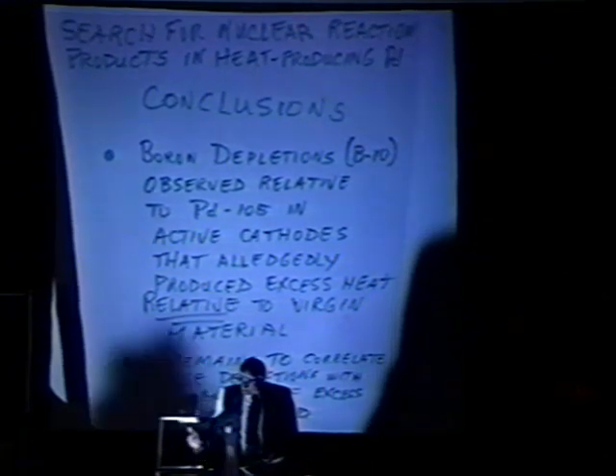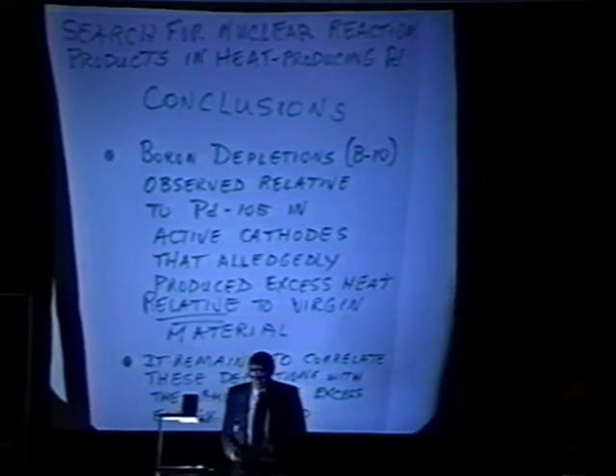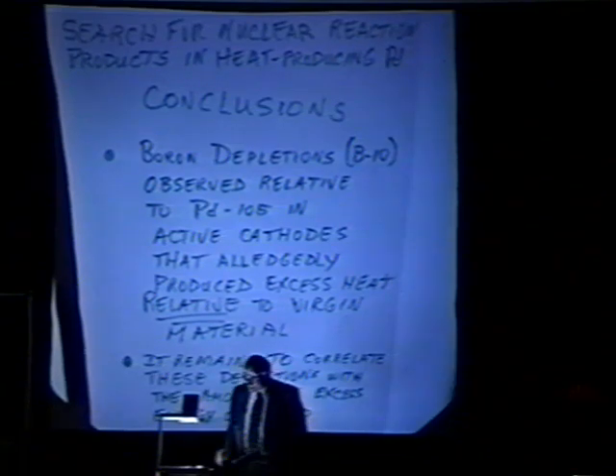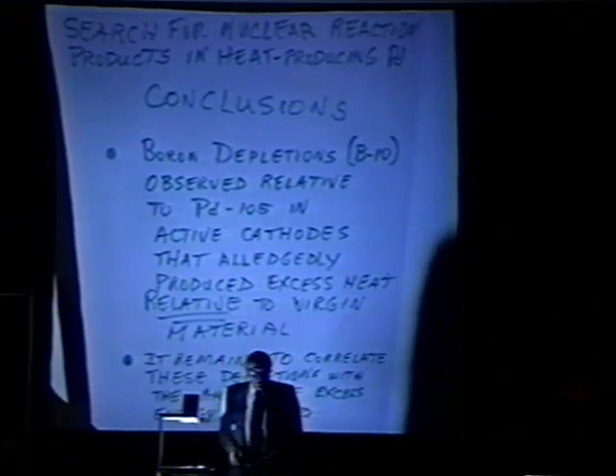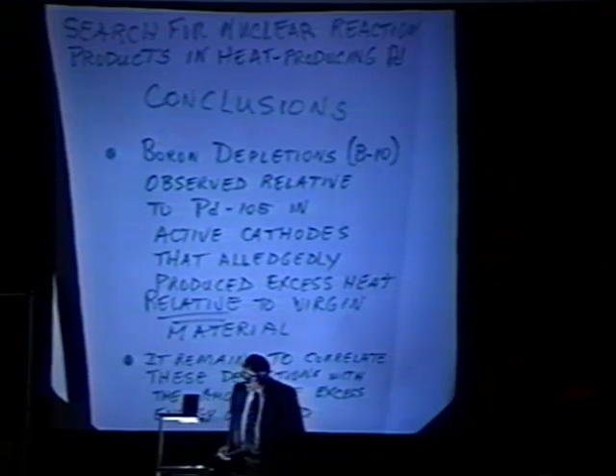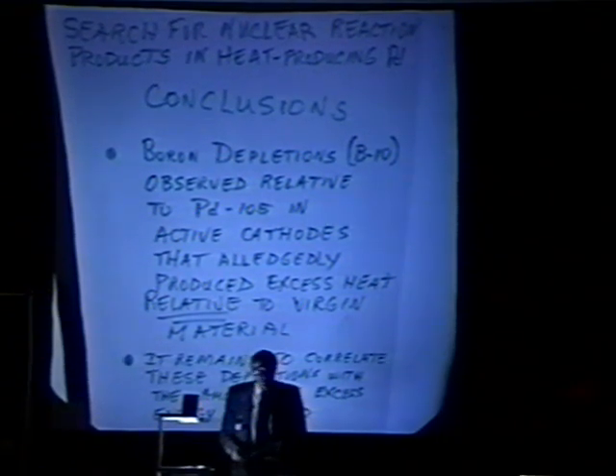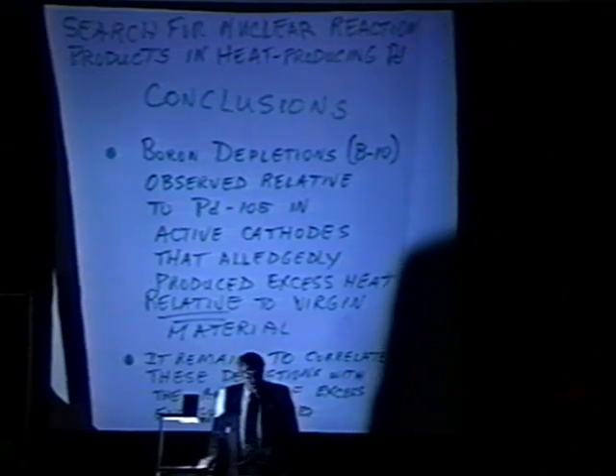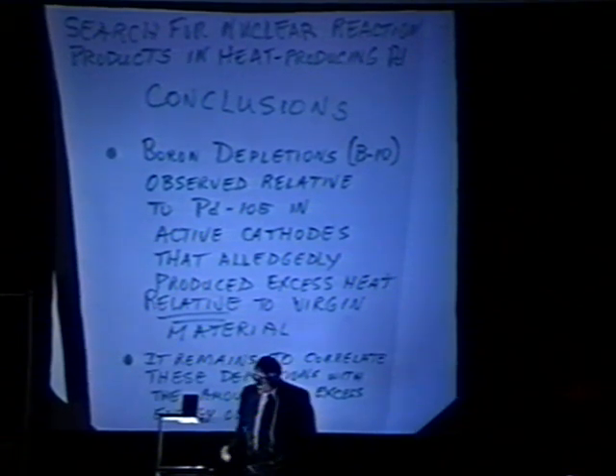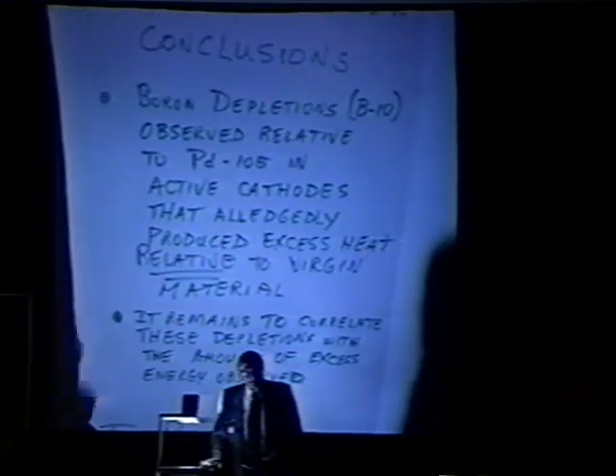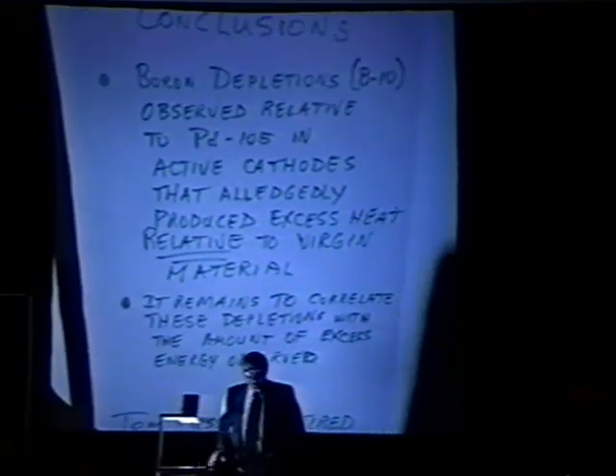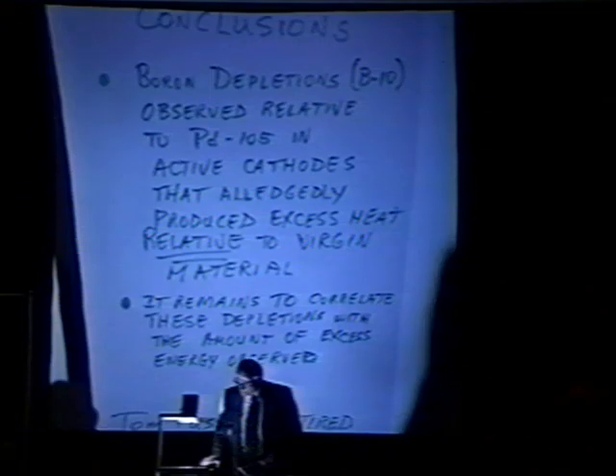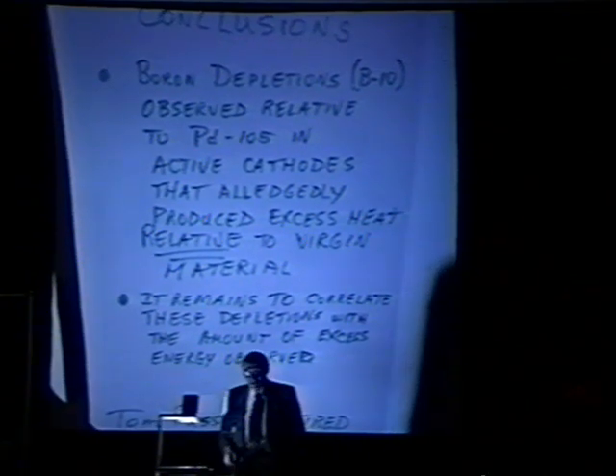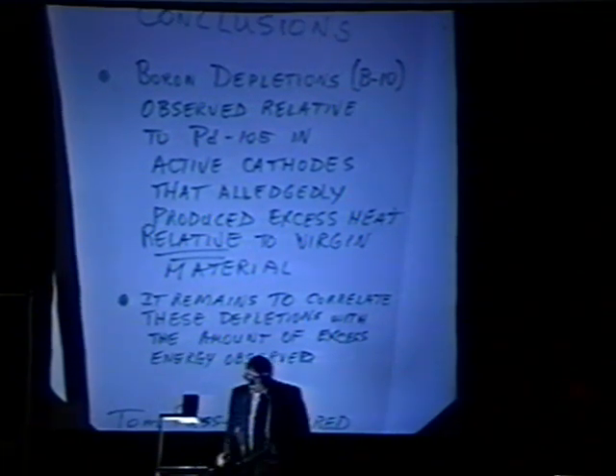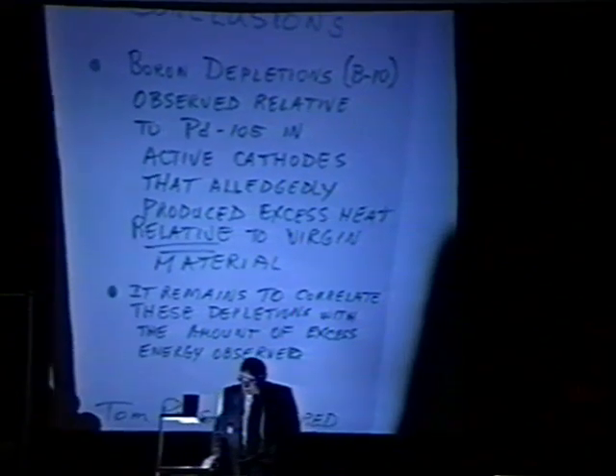And I observed its ratio to palladium-105, one of the main isotopes of palladium, in the heat-producing palladium relative to the virgin material from which that cathode originally came. And we, of course, assume that that particular batch of palladium is the same and uniform throughout, which is not by any means yet proven. And it remains to correlate fully these depletions that I've observed with the amount of excess heat observed.